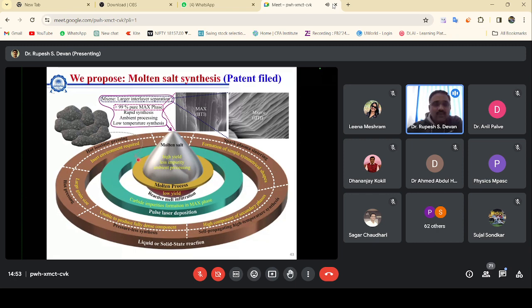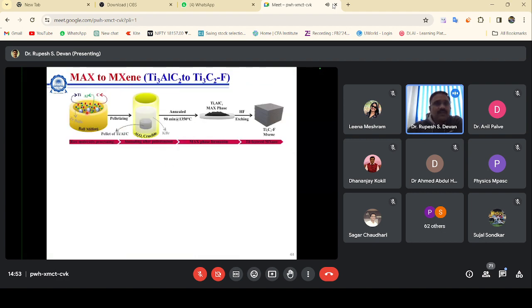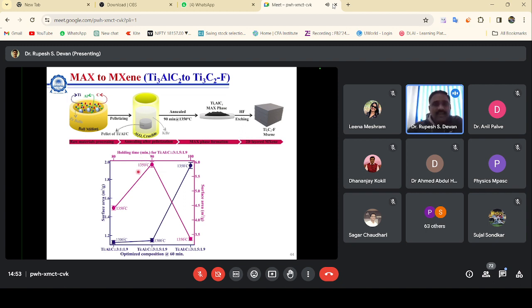So here what we did, rather than going for high vacuum techniques like pulsed laser deposition or spark plasma sintering or solid-state reaction, we modified this process and came up with an idea of molten salt synthesis which can operate at ambient atmosphere rather than using high vacuum. And you can see here, these different concentrations have been mixed together in an alumina crucible and reacted at 1350 degrees Celsius, and then nice MXenes are being observed over here. And then you can see the surface area has quite increased. So at one particular temperature, with different reaction parameters, 99% pure MAX phase is observed.